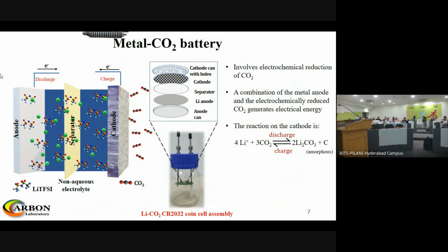So unlike typical energy storage devices, it's not a closed system, it's an open system where CO2 is continuously pumped towards the cathode. The lithium ions go through the separator and react with the CO2 on the cathode. These lithium ions react with the CO2 and form lithium carbonate plus carbon. So it's basically a combination of a metal anode and electrochemically reduced CO2 which generates the energy in this process.